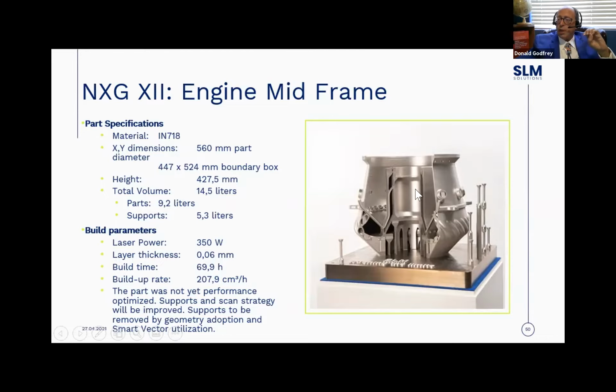So on a part this big, you may get 20 or 30 tensile specimens just out of this region right here. You may take some out of this region right here. You want to know about orientation effect. So you see this rim that goes around here. You may cut some specimens out of that rim. Once it's qualified, you only have to do that during the qualification process. During the production runs, it's up to your customer and your quality department, but you may only have to build test specimens on the side.